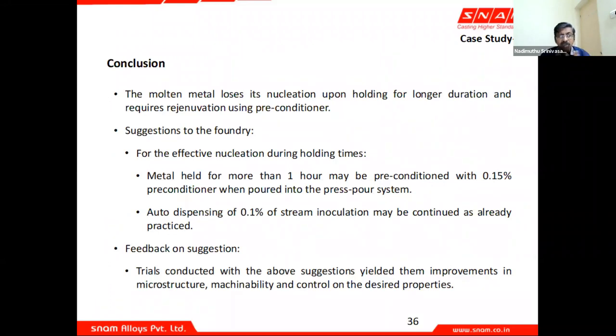So what happens? The molten metal loses its nucleation upon holding for a longer time. Suggestions to the foundry were to provide effective nucleation during holding time: metal held for more than 1 hour to be preconditioned with 0.15% of preconditioner, and their auto dispensing of 0.1% stream inoculation can be continued. Based on these suggestions, they were able to implement it and get over the problem of machinability.